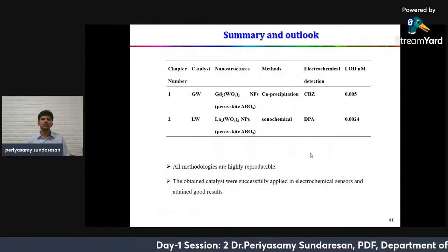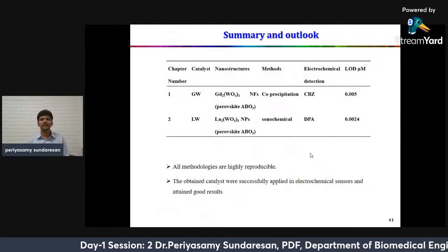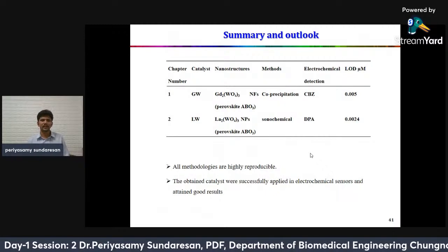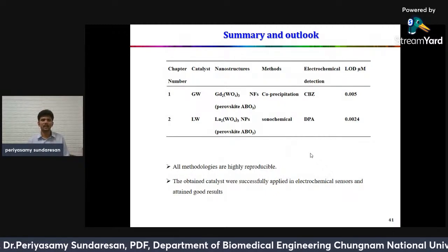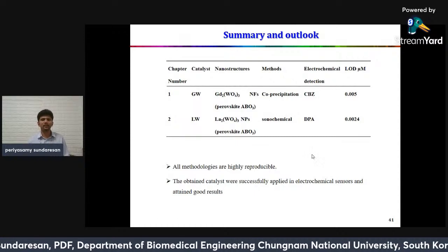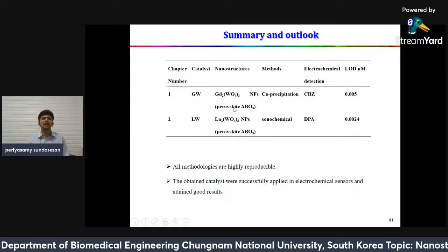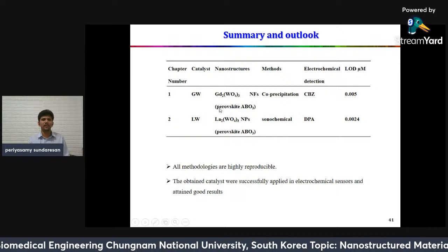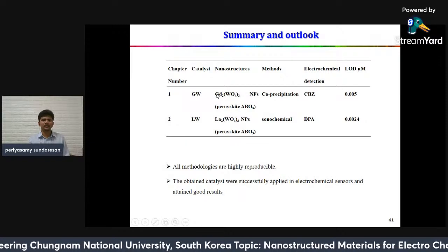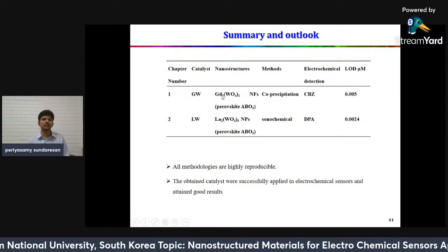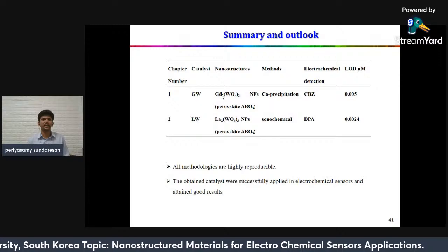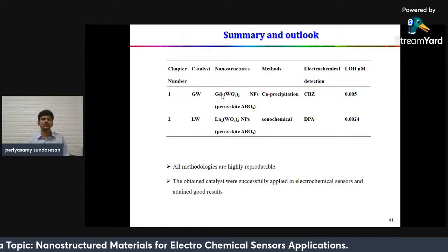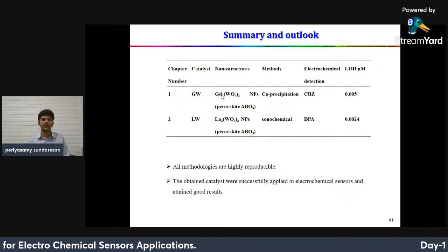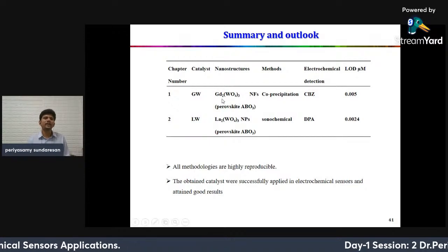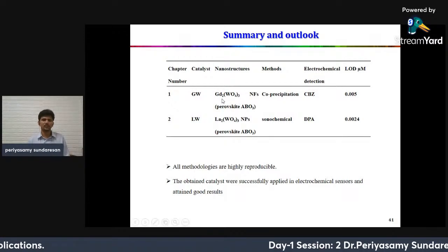The summary and outlook of the work. Here I have prepared 2 different catalysts, the gadolinium tungstate and the lanthanum tungstate. This is a perovskite oriented material, a rare earth metal oriented element. Compared to other noble metals, the rare earth metal is a very cheap material, and it can easily form a perovskite structure.